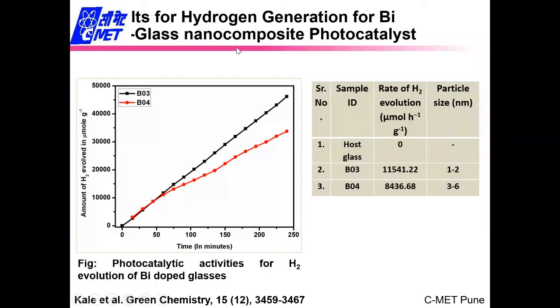Then we developed bismuth nanoparticles in the glasses, and we found that bismuth is giving very high photocatalytic hydrogen evolution. 11,542 micromoles means almost 2 liters per hour of hydrogen evolution, using very small particles, 1 to 2 nanometer. In the glass, they give a good amount of hydrogen. So we published in Green Chemistry, a Royal Society of Chemistry journal, a very renowned journal. Maybe now the impact factor is 10. We have good hydrogen production. Now we are thinking how to commercialize it for water splitting and H2S splitting.